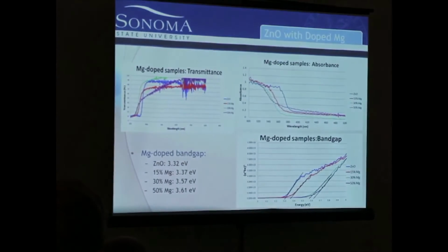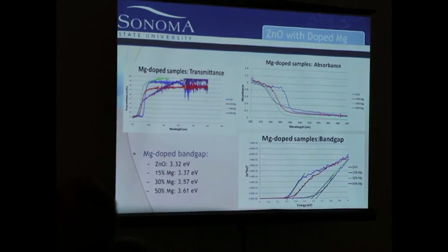So this is the data that I use for zinc oxide doped with magnesium. First we get our transmittance data, and that's just to check the transparency. That's a big part of this project because we want it to be at least 70% transparent or higher. That's just for quality because we want the photons to be able to really go through. The blue line is the zinc oxide, and we can see that it's at about 90% transparent, which is good. Then we have 15% of just the magnesium, which is this red line, which is about 75%.